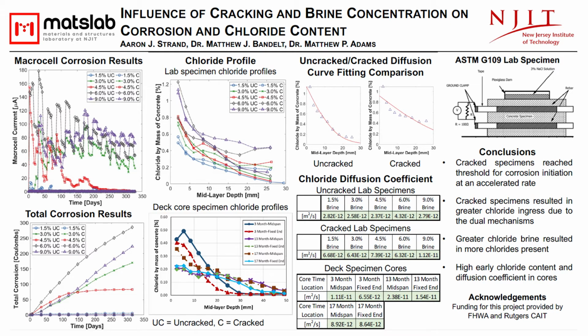After the macrocell corrosion testing was completed, powder profiles were taken of each specimen in which the acid-soluble chloride content was found. From the bridge deck specimen, cores were taken at different times and profiled for acid-soluble chloride content. The acid-soluble chloride content results were used to calculate the apparent diffusion coefficient and the chloride content of the deck surface.